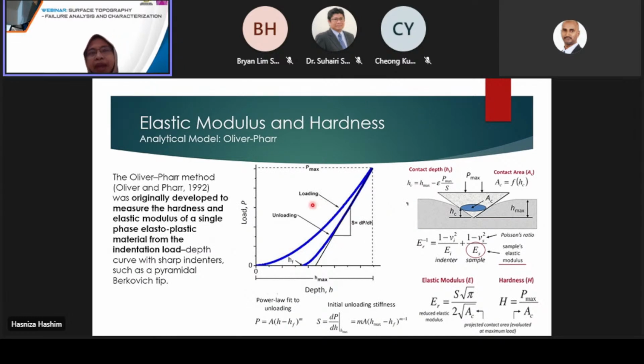So just now we have done the indentation. Now from the indentation testing, we have this force and displacement curve. This is the force and displacement curve from a single indent on fused quartz. As you can see here, the loading curve has a parabolic shape since the contact area between the probe and the sample increases as a square of displacement into the sample. Thus, more force is required to displace the probe into the sample. As one can see here, this loading curve is not lined up with the unloading curve. During loading, plastic and elastic deformation occurs. Upon unloading, the plastic deformation is retained and the stored elastic energy is recovered.